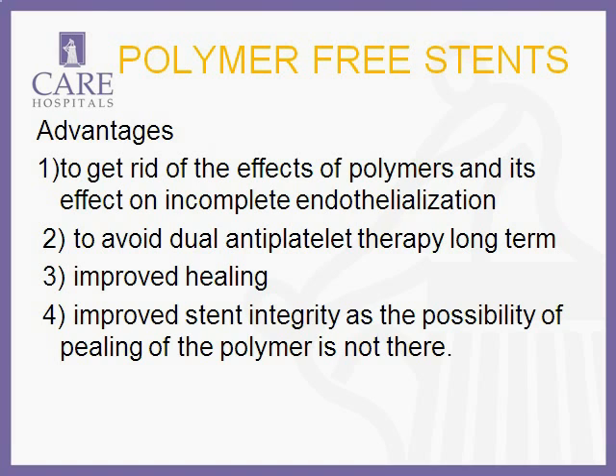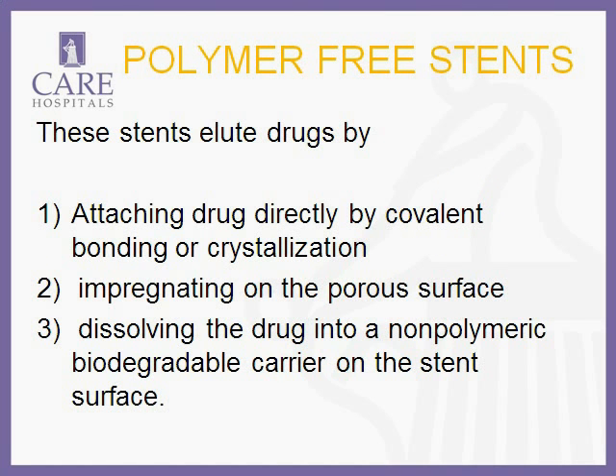The polymer-free stents avoid the problems with polymers, as they have advantages in terms of getting rid of the polymer issues of delayed endothelialization. It also acts like a bare metal stent after the drug is eluted, and therefore we can avoid dual antiplatelet agents in the long term. It improves the healing and also improves the stent integrity because of the absence of peeling of the polymer.